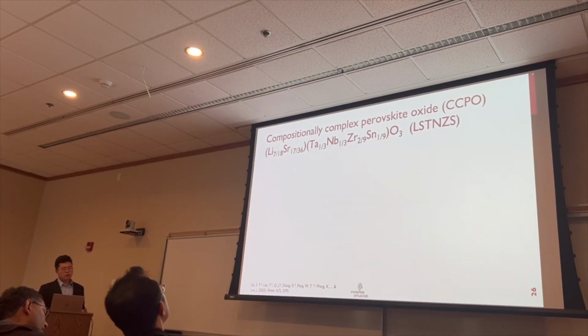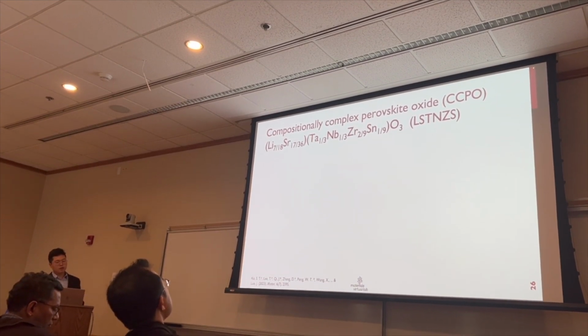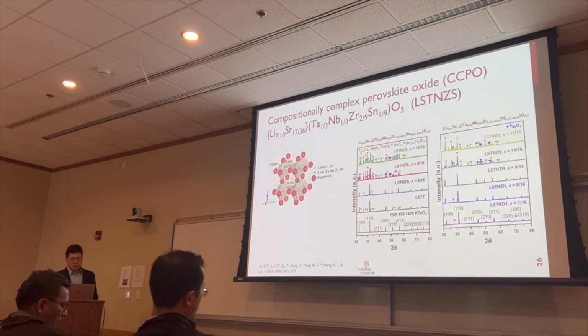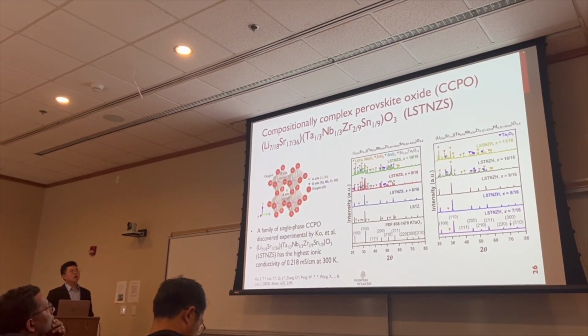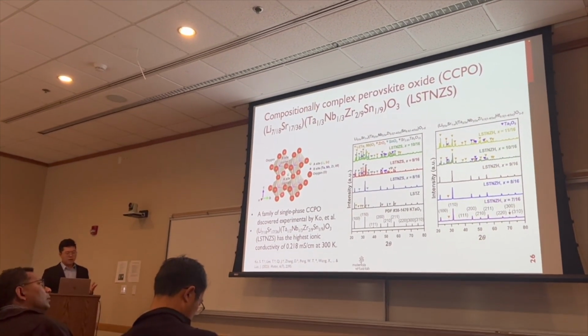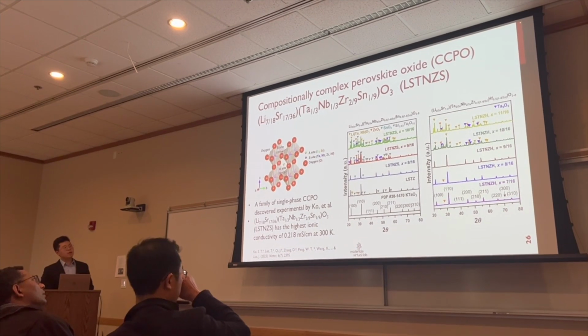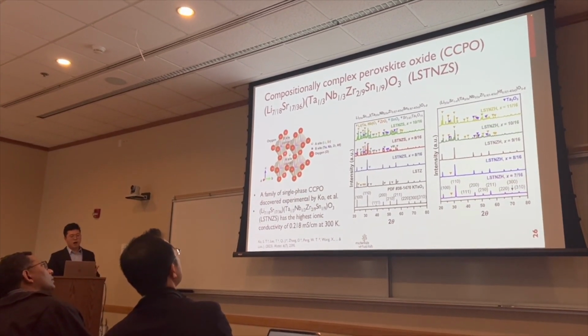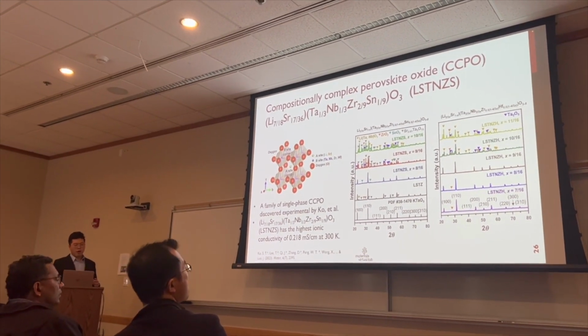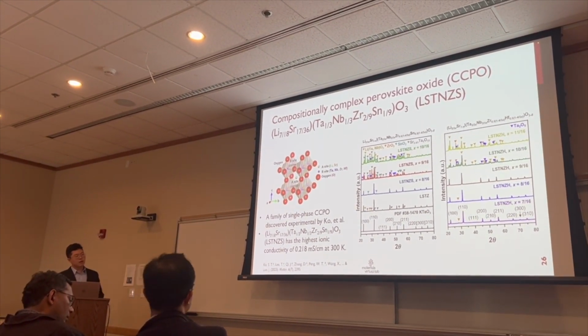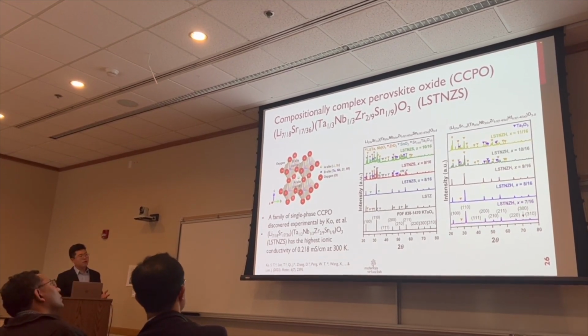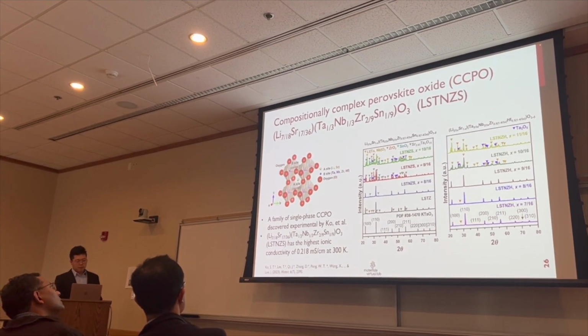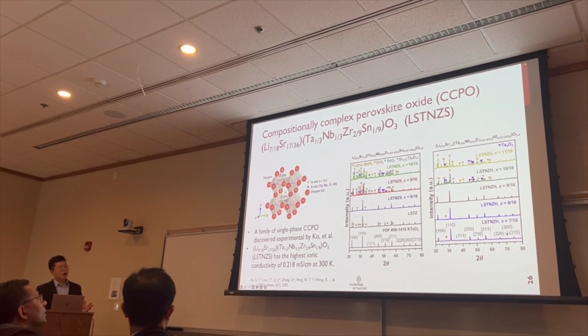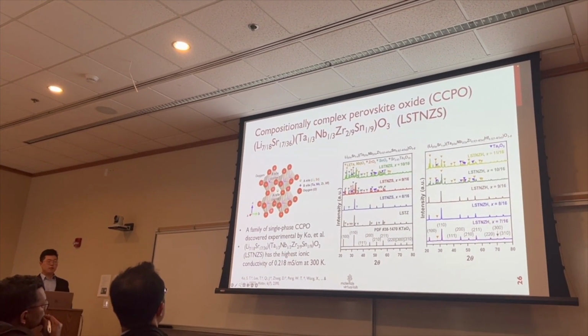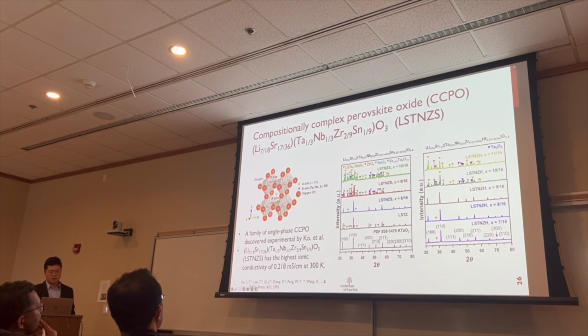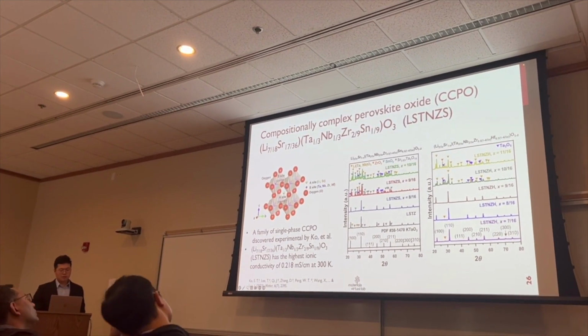And we also continue to study this system by looking at the compositionally complex perovskite oxide. For this work, our collaborator, again, Shuting Kou from Dr. Jian Luo's group at UCSD, discovered this new family of single-phase compositionally complex perovskite oxide that can have 4 elements on the B site of this oxide perovskite. Those can be tantalum, niobium, zirconium, hafnium, or tin. And this composition of LSTNZS has the highest room temperature ionic conductivity of 0.218 millisiemens per centimeter. So that's why we're going to study this system.